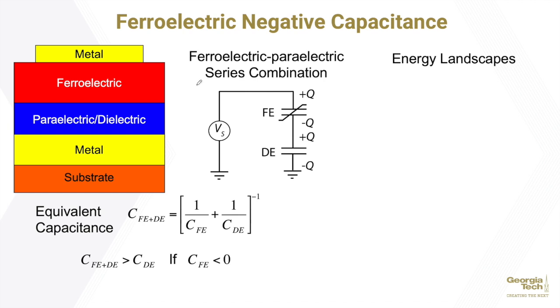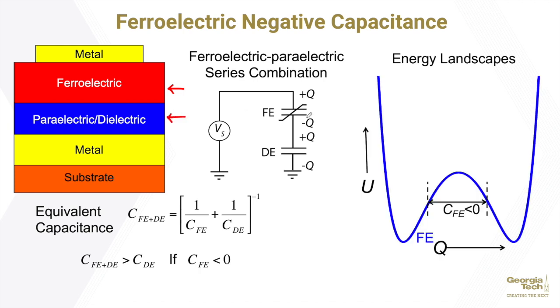So how can one access this negative capacitance region in a stable experiment? In other words, how can one stabilize this negative capacitance state? One way of stabilizing this unstable state is to fabricate a heterostructure containing a ferroelectric layer and a paraelectric or a dielectric material. The stabilization mechanism can be understood by looking at the energy landscape again. The blue curve over here represents the double well energy landscape of a ferroelectric material, and the black curve over here represents the energy landscape of the paraelectric material.